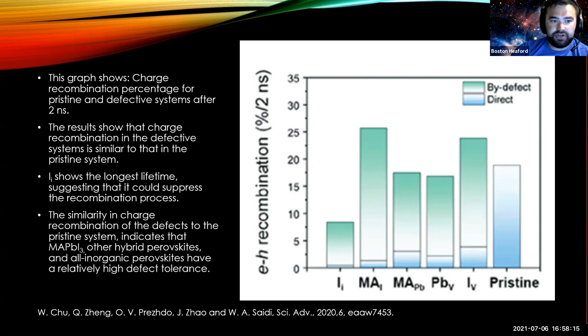So the similarity in charge recombination of the defects to the pristine system shows that the methyl ammonium lead iodine perovskite has relatively high defect tolerance, so the defects don't affect it that much. And they said for other hybrid perovskites as well, will likely have a similar defect tolerance.